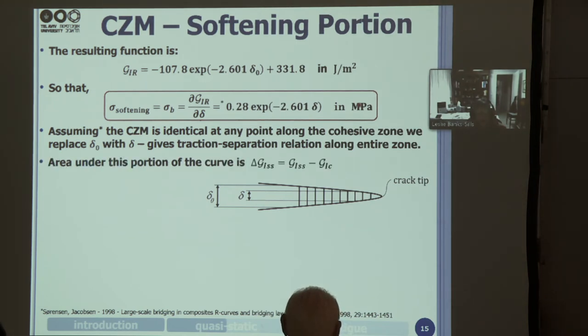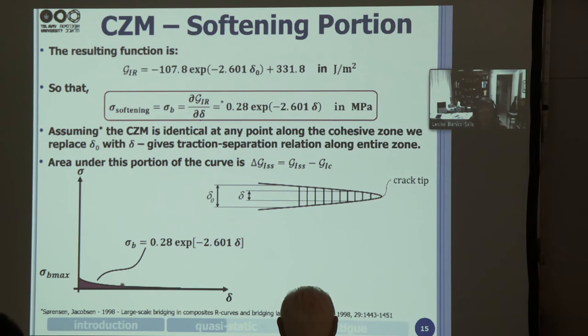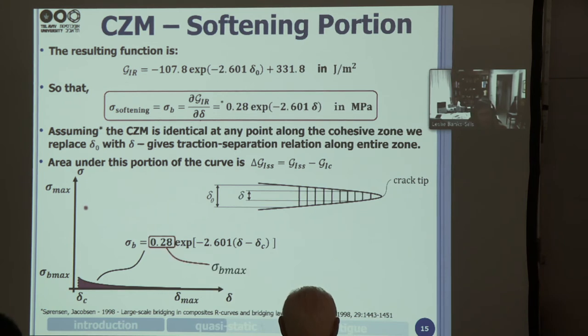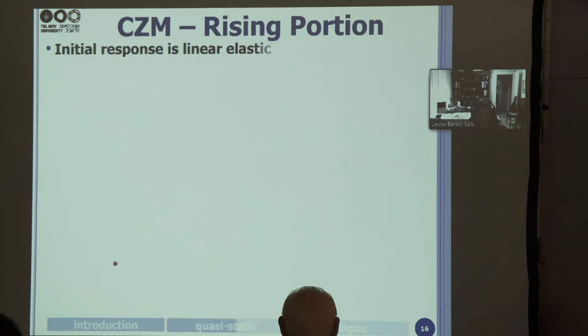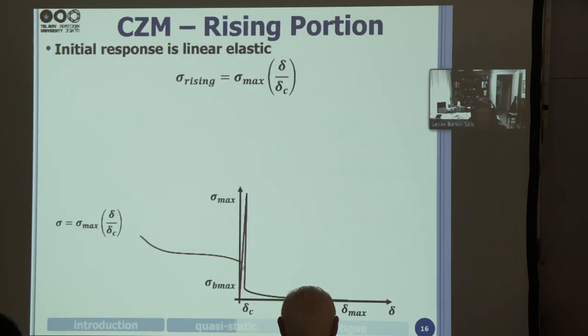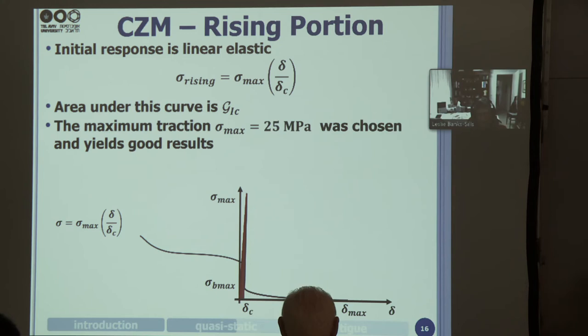So here we replace delta naught by delta, and this is the softening part of our traction separation law. The area under this curve, the pink area, is delta G1SS. And this is our curve, and this is the softening part. Of course, we can get sigma B max when delta is equal to zero. But what we do is translate the curve because we want to allow for the initial increase to sigma max. So this is sigma B max, and here's our initial response, which is linear. The area under the curve is G1C. And now we also have the softening part.